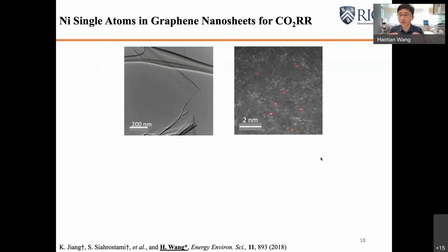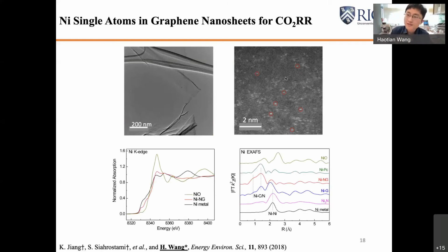And we just directly start with graphene nanosheets, where we have a lot of defects pre-created, and then we spray coat trace amounts of nickel atom precursors, and we do a thermal annealing, and those nickel atoms can be automatically sucked into the defects to form these atomic sites without direct nickel-nickel coordination. And this becomes a much better materials platform for us to use X-ray absorption spectroscopy to understand better about